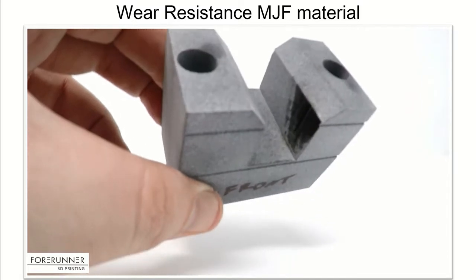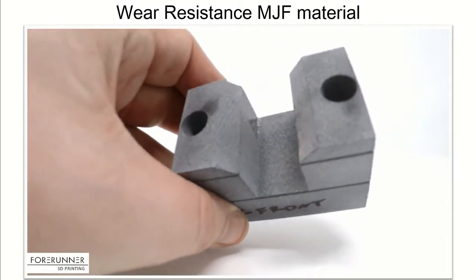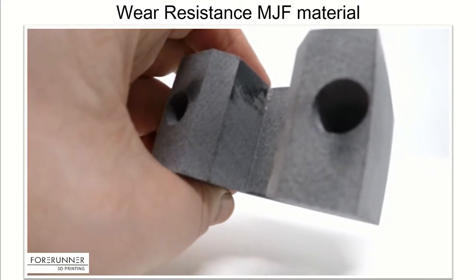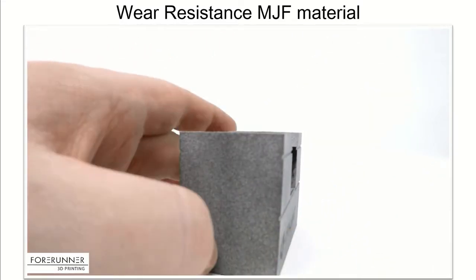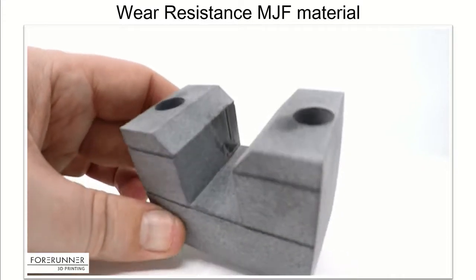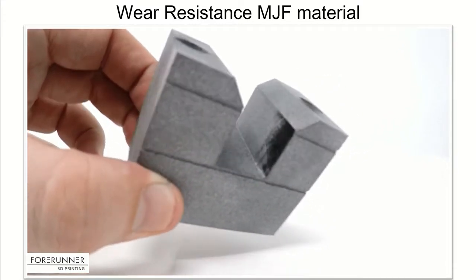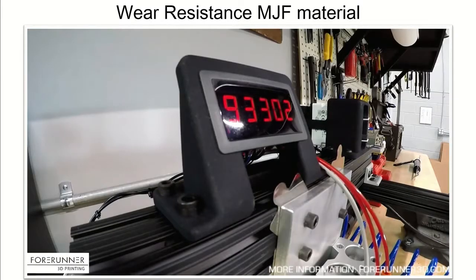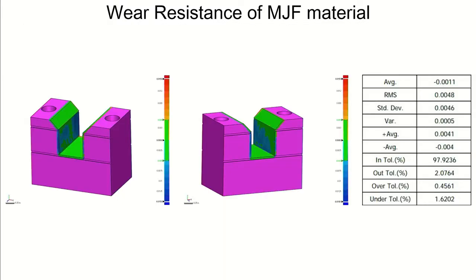And over that 100,000 cycles, it actually forced the detail to twist. We didn't actually dowel the detail in place, so that was a mistake on our part, but it forced the detail to twist a little bit. So that's why you're seeing corner to corner wear. But the worst of the wear was only about 13 thousandths. So this is a laser scan inspection report that we did of this detail after the 100,000 cycles. And you can kind of see for yourself, you've got the really dark blue ditch on the left-hand view, kind of up towards the upper right-hand side of the part. That's 13 thousandths. Other than that, everything's kind of in that 5 to 6 thousandths range of wear.